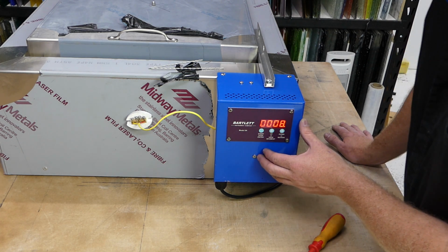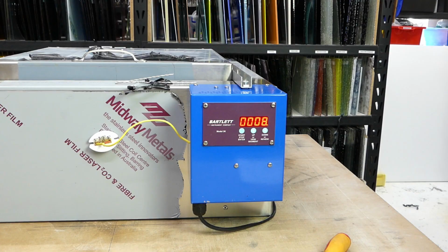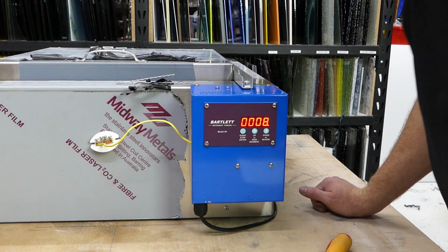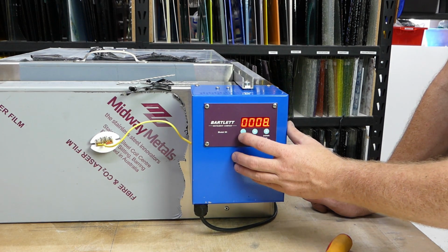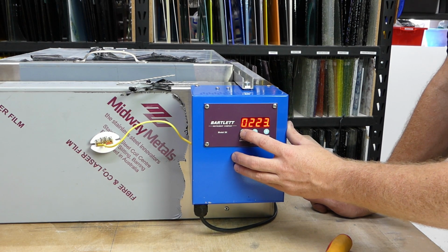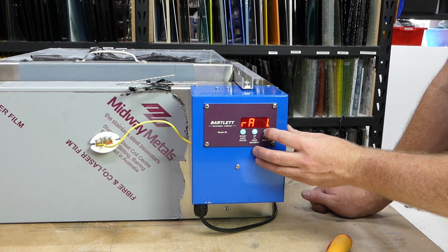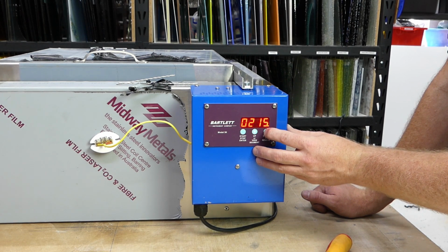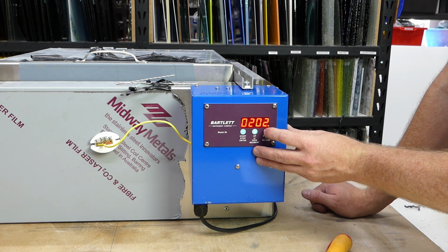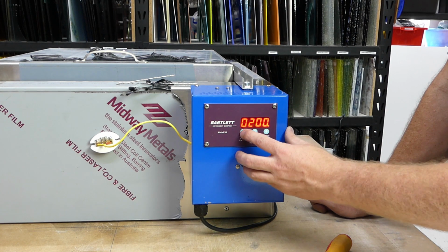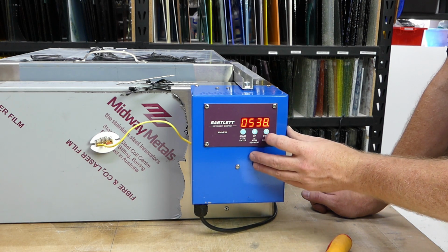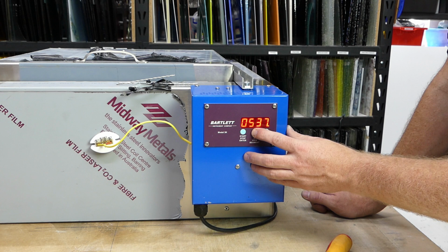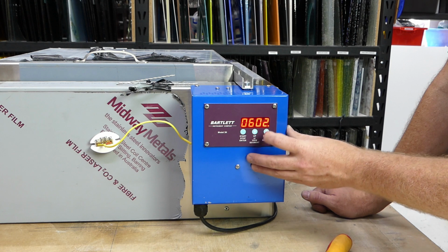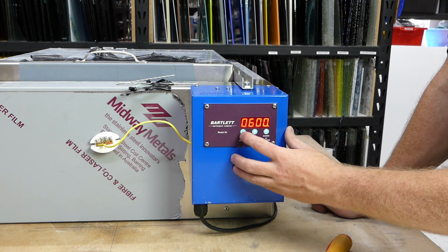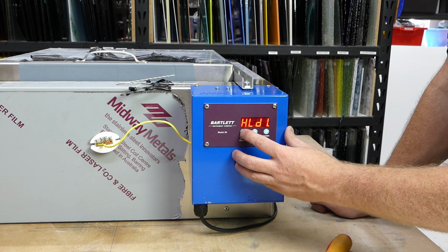I might just adjust that camera angle while we're on the 8 segment part, just to make sure you can see it nice and clearly. Okay, so we want 8 segments, we press enter. If this is our first ramp speed, we're going to go up at 200 degrees an hour. 200 degrees an hour is pretty much the maximum safe speed if you're going to be running up to a 400 by 400 shelf. And our target temperature for this one is going to be 600 degrees. This is our bulk heating firing. And we don't need a hold for this segment.